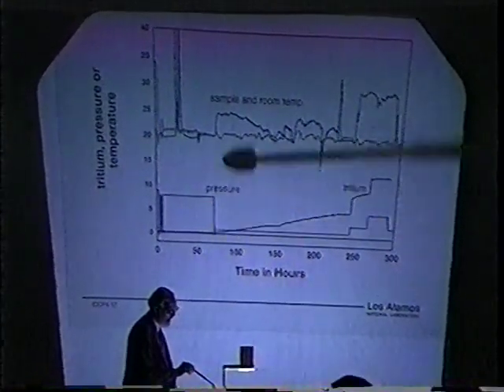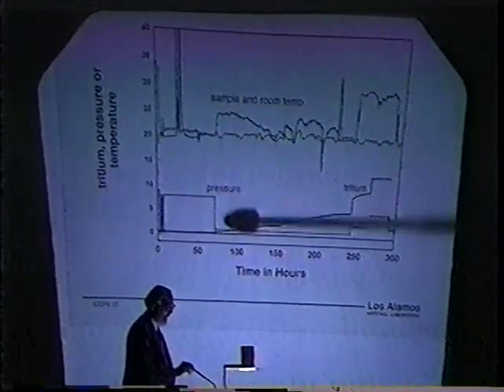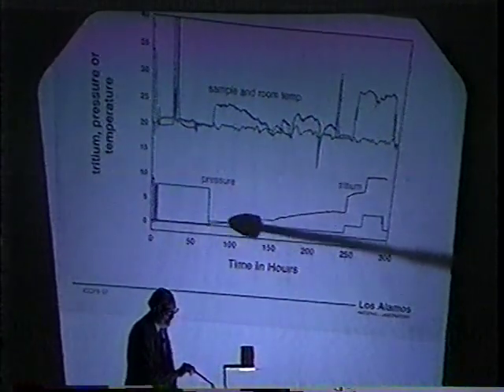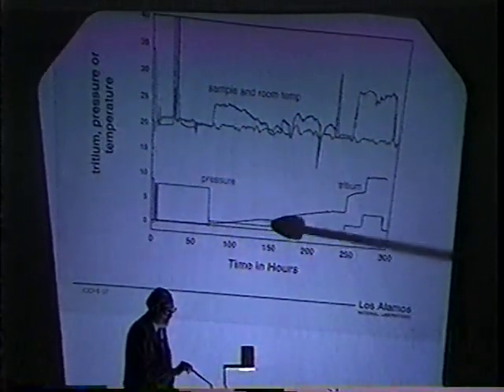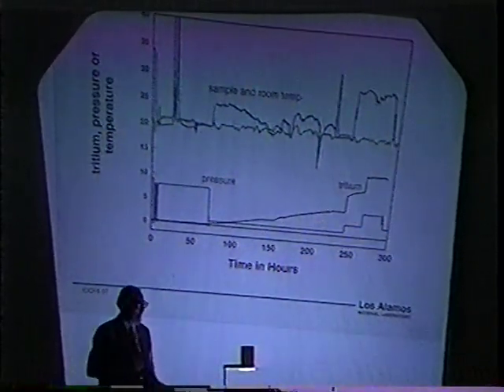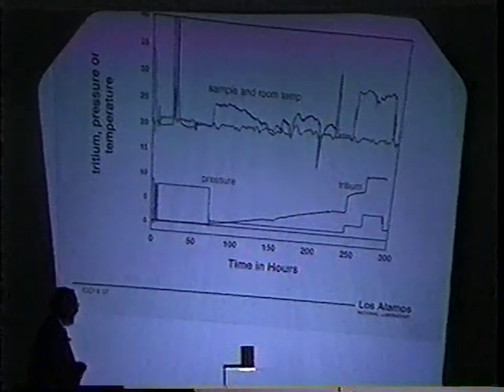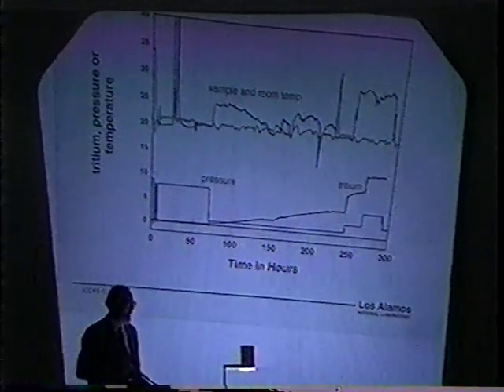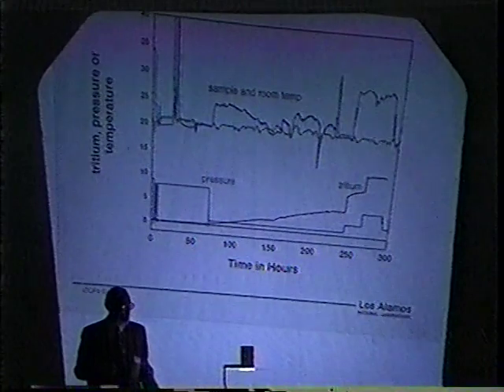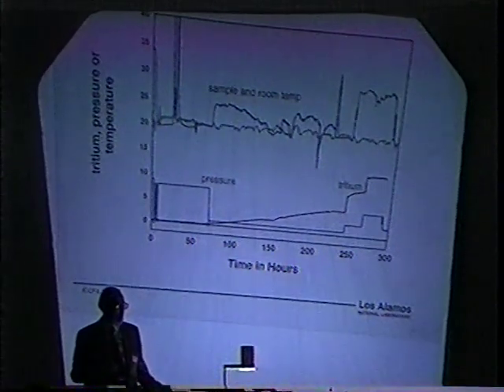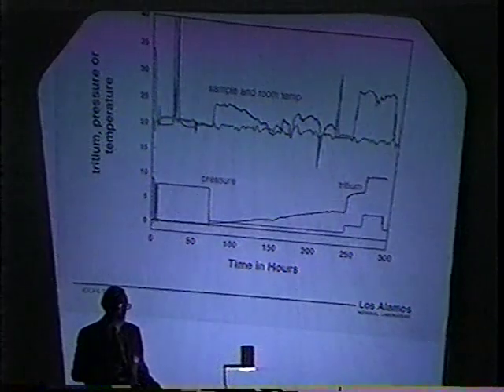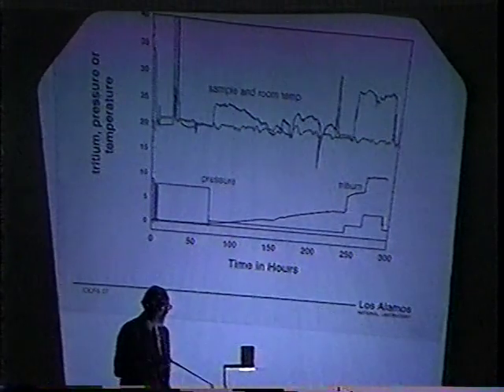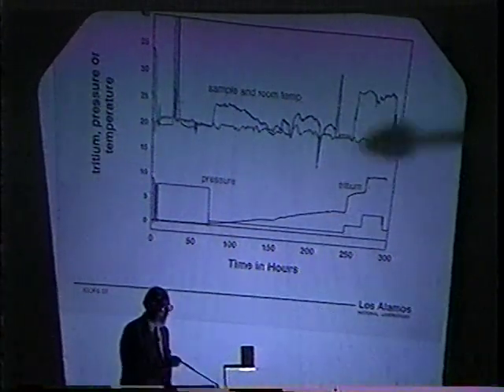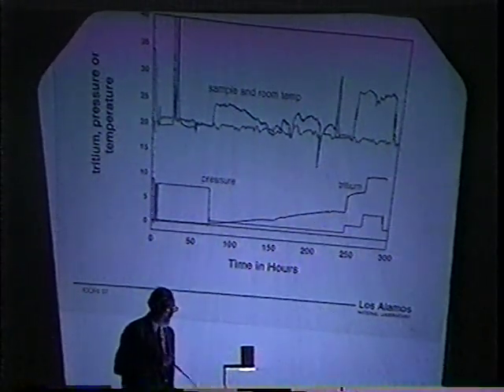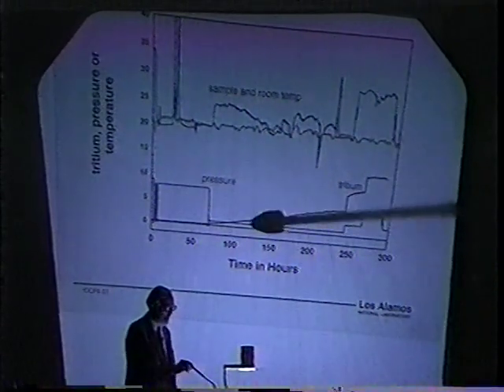So the discharge starts here, the temperature of the cell rises, and the pressure remains constant, but the tritium proceeds to rise. The best tritium level is about 100 times his sensitivity. Typically, he gets tritium levels that are 5 to 10 times the sensitivity. So it's well above the background, and you can see here that this is clearly resolvable from 0.